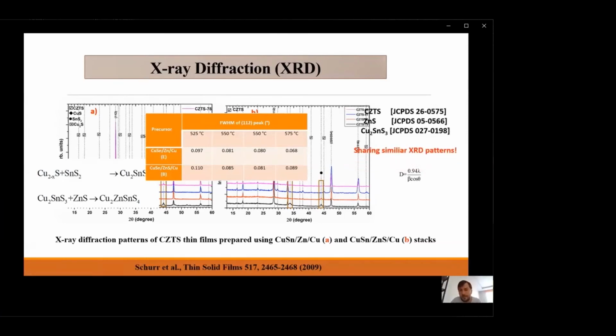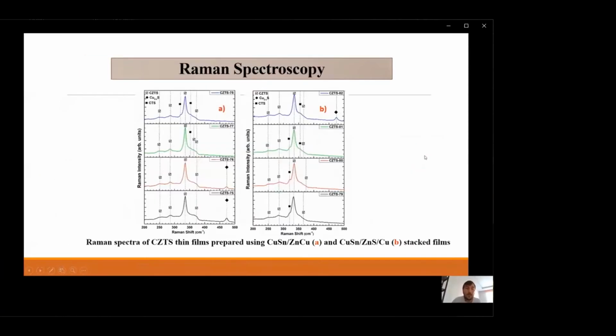But of course, the XRD is not enough for distinguishing the CZTS phase, because CZTS, zinc sulfide, and CTS thin films share similar XRD patterns. So we need a complementary technique. This is the Raman spectroscopy. As you can see, the Raman spectroscopy also gives us the phases and distinguishes these phases from each other.